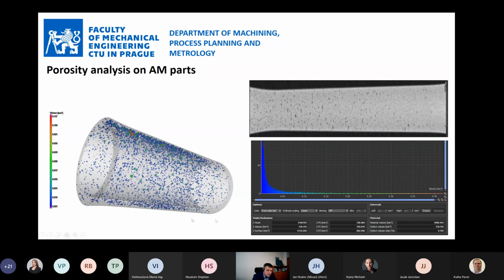This is one of the analyses which can be provided by computer tomography. This is a midsection of samples for high fatigue cycle testing. And you can see that there is quite significant porosity. This is the original 2D image from the CT scan. You can see the visualization of the pores here in 3D, and you can get also some kind of statistics. So you can see that this sample was actually very bad, and it had more than 4% porosity. On the histogram, you can see the distribution of the pores. You can see the location and the size of every single pore within the resolution. And the resolution is something like 1/100th, 200th of a millimeter on steel, which is attainable. Maybe I should mention that this is not our product. I don't want to mention the party which was printing these samples, but this is some real data analysis made maybe 1 week ago.